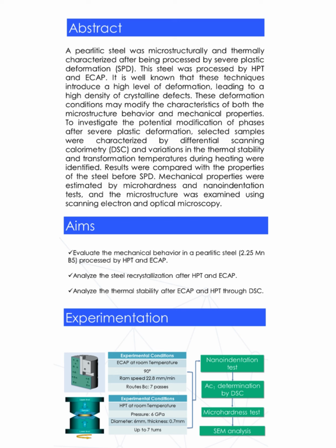For HPT, the sample was pressed with a force of 6 gigapascals, and one of the anvils of the press was rotated 360 degrees clockwise. The samples underwent up to 7 turns. After processing by one of the two SPD techniques, selected samples were characterized using differential scanning calorimetry, DSC. Mechanical properties were estimated through micro-hardness and nano-indentation tests, and the microstructure was examined with scanning electron and optical microscopy.